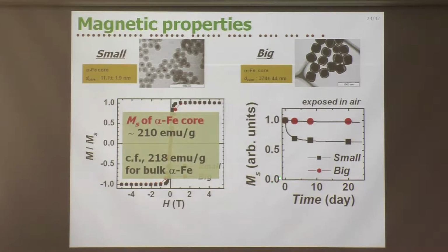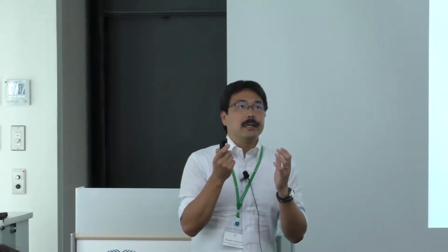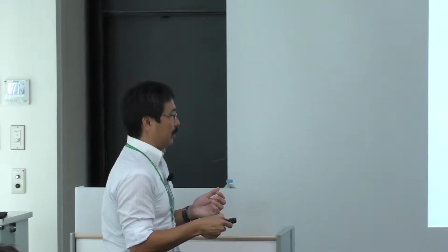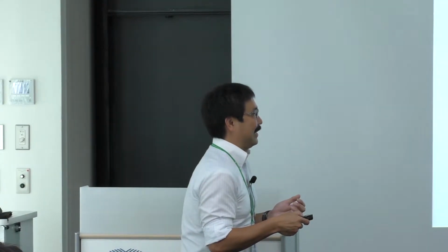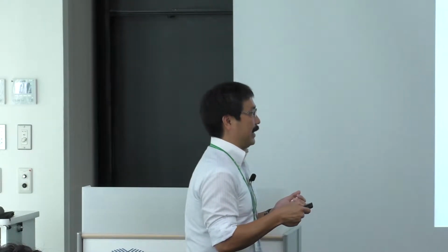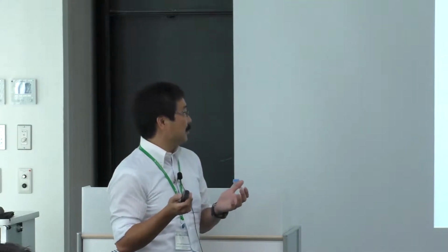Here shows the time evolution of the saturation magnetization of the sample after exposure in air. If the alpha iron oxidizes, the saturation magnetization will be lowered. As you can see, for the smaller sample, the saturation magnetization is decreasing upon exposure to air, so the samples are oxidized even when coated with SiO2 shell.